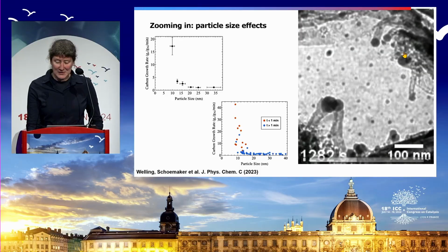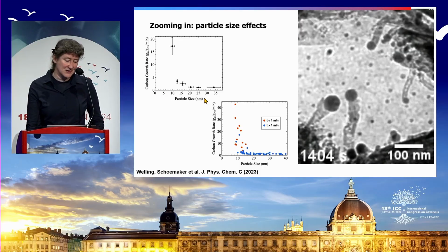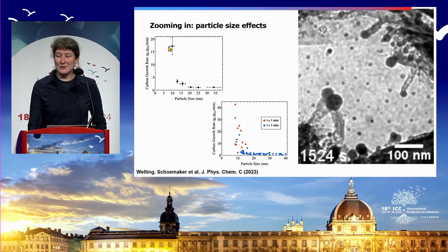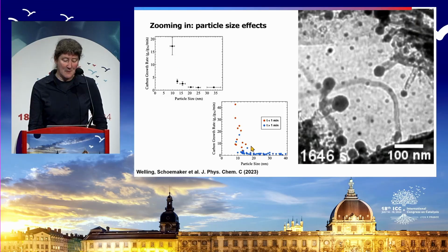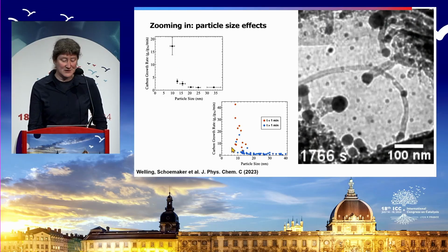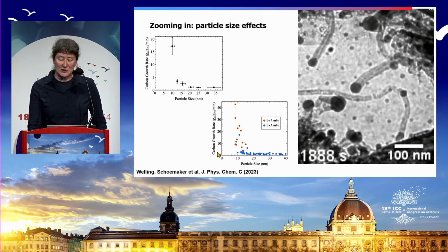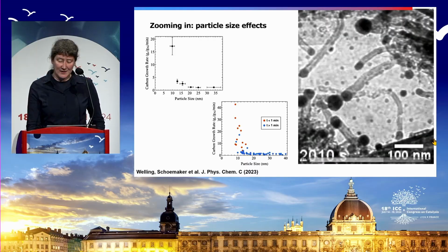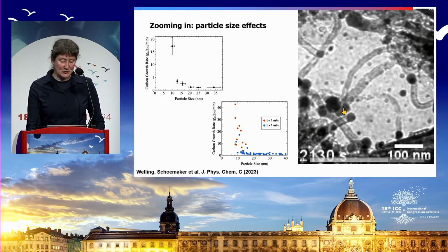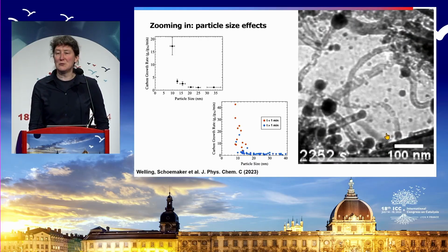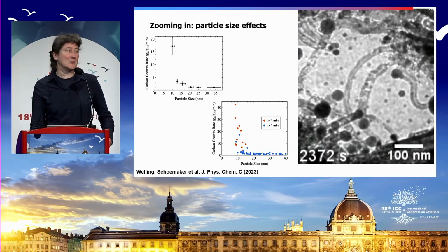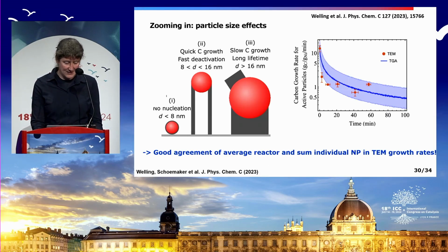So you can really immediately see, as a function of particle size, initially the small ones are very fast. But they also deactivate fastest, so after a while, you only have the large ones that are still growing. There's this really speedy Gonzalez type of particles, and you also see at some point it gets very full. This is also a practical limitation of the process.